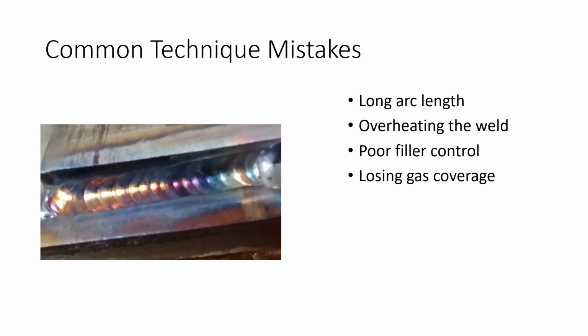With gas tungsten arc welding, especially with things like duplex stainless steels, a lot of times we want to have minimal heat input into these materials, because if you have too much heat, it can do a lot of weird stuff to them in the material strength and mechanical properties kind of way. And it can damage them metallurgically and corrosion resistance wise. So if you're dealing with stainless steels, overheating is really important that we don't do that.